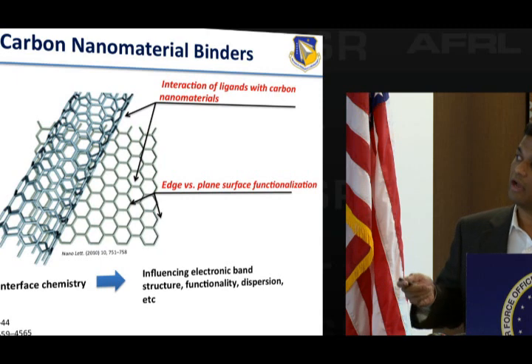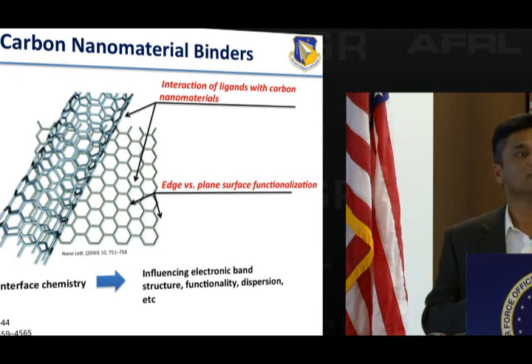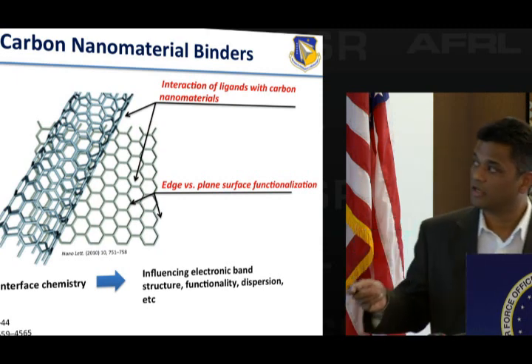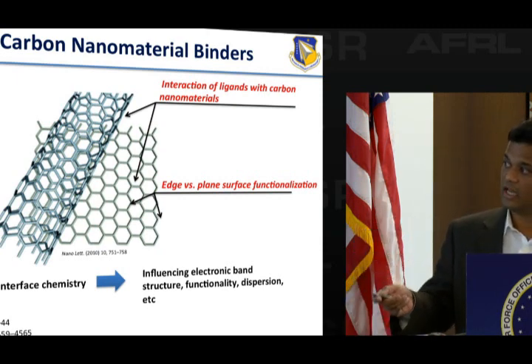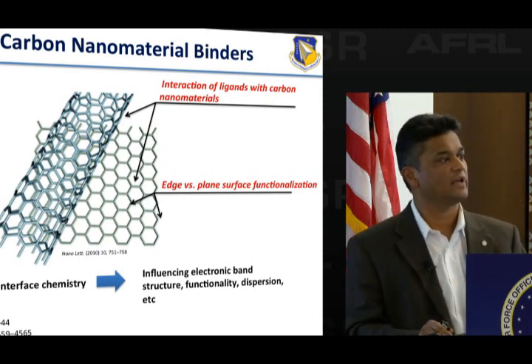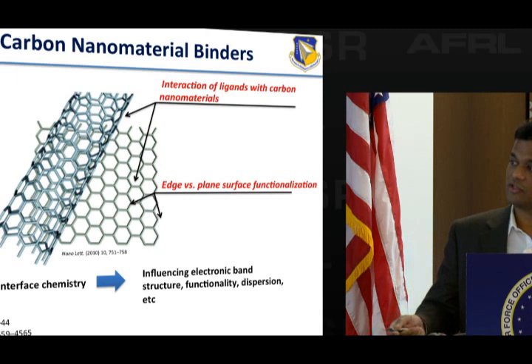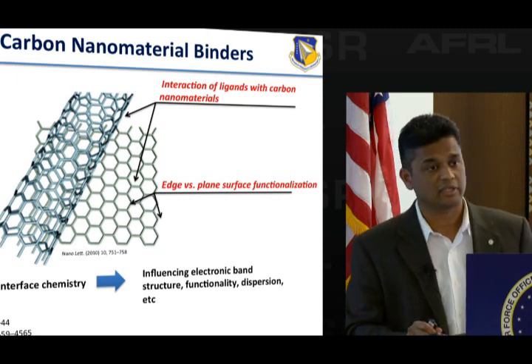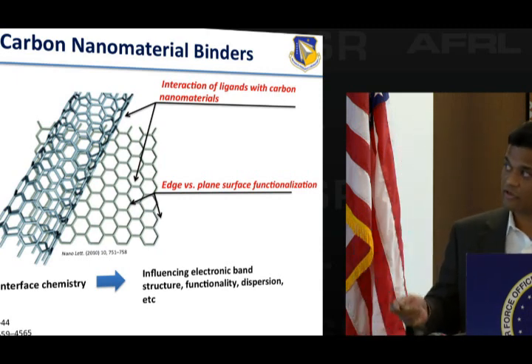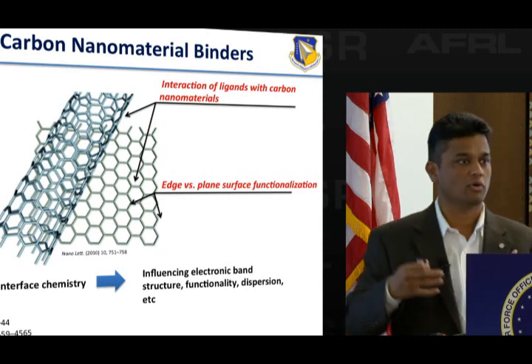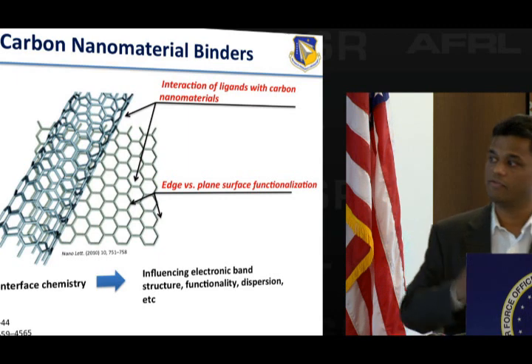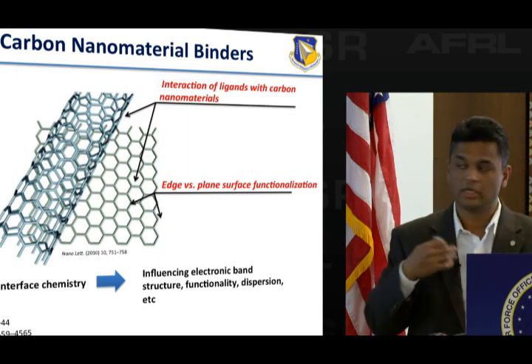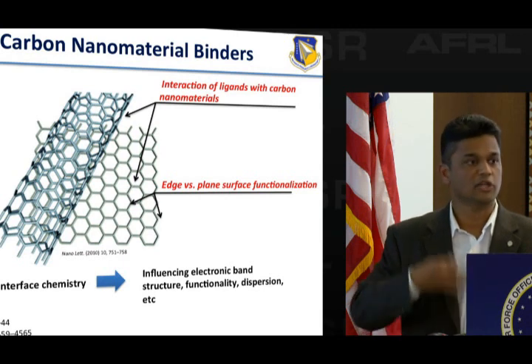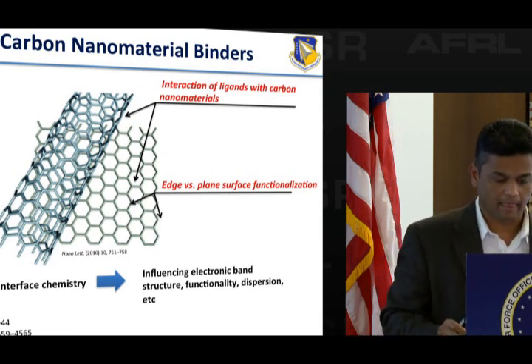And with graphene, it's not just a planar sheet, but you also have edges and plane, which give you maybe an additional parameter that you can screen for, looking for things that bind to the edge versus the plane. Can you identify peptides that have that kind of selectivity? The reason for this is that surface chemistry and interface chemistry on these carbon nanomaterials does influence electronic band gap structure, functionality, dispersion, and so on and so forth. The driver has always been trying to identify non-covalent interactions, so you don't want to introduce defects into some of these materials. So if you can use a peptide-based route to non-covalently interact, can you preserve some of the intrinsic properties and use that to build devices or other materials that are of interest to us?